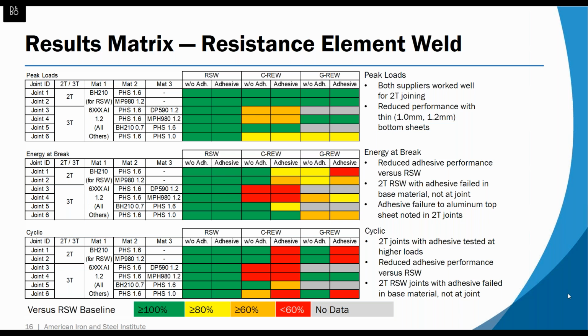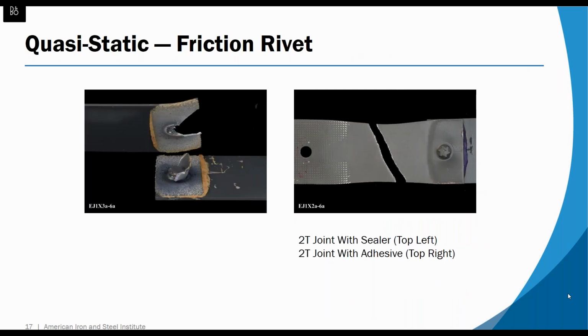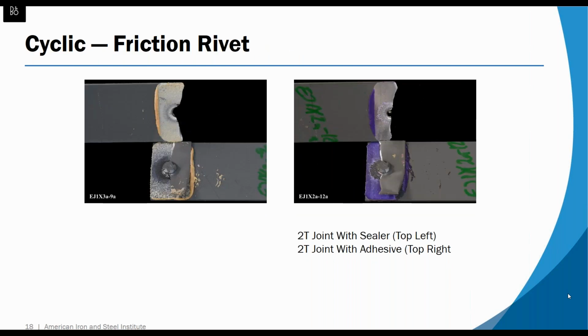In the case of the adhesive, we saw a change in failure mode in the two-thickness that caused some reduction in life. The final joining method I'm showing today is the friction rivet, and you can see we only have two-thickness joints because, as I mentioned previously, the technique only works for two-thickness joints. On the left, we see a pretty typical tear-through like with the resistance spot weld. On the right, with adhesive, it was again very similar to resistance spot weld.